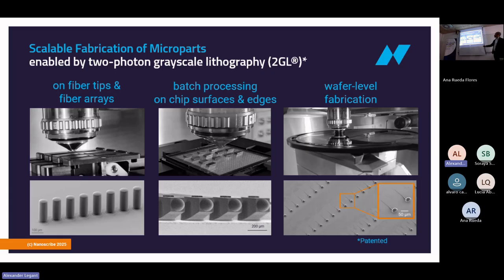You can also print edge couplers. We use a pattern to compensate. Of course, you focus from the top, but if you do edge coupling, you have some shadowing effect directly at the edge, and we compensate the laser power directly to always have sufficient laser power to trigger the chemical reaction. And like what we see over here on the right side, you sometimes work with whole wafer levels, with whole wafers, and print the optical elements directly, aligned and automated, on these types of wafers.